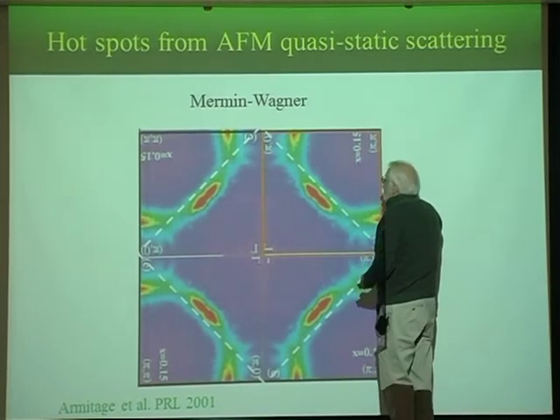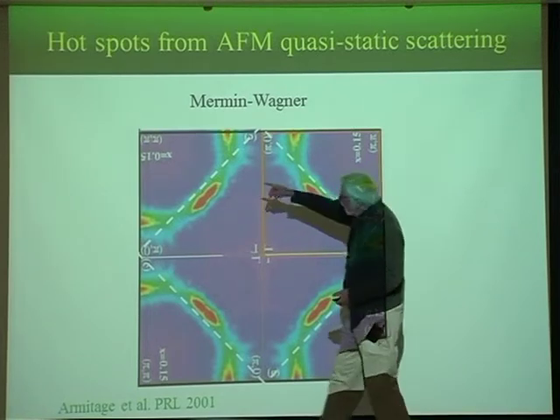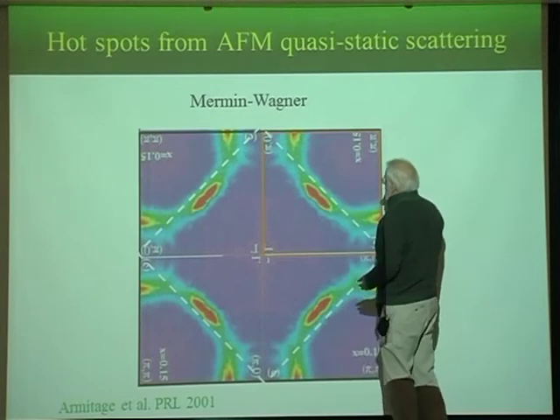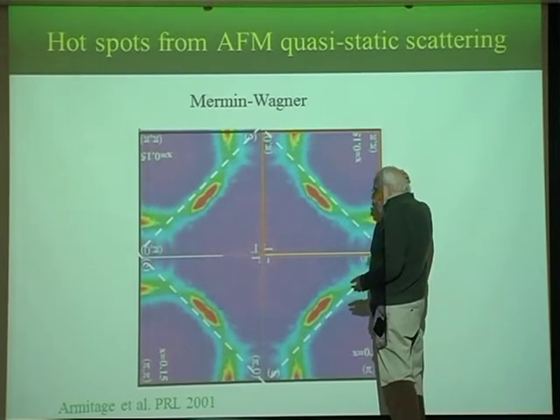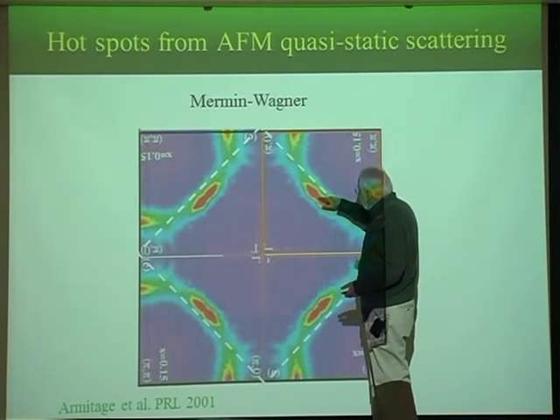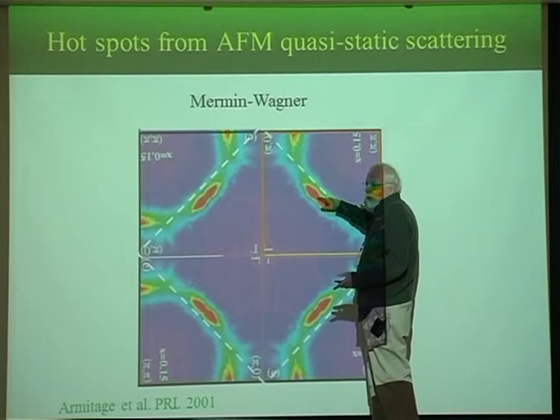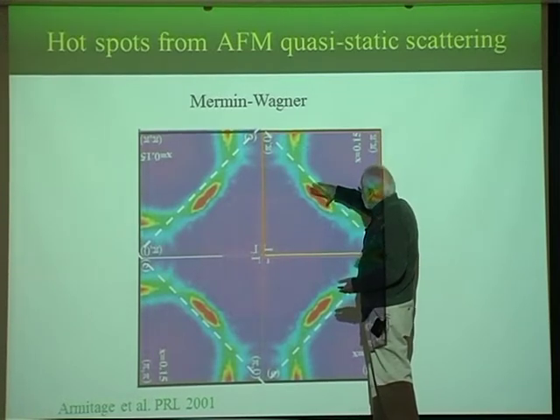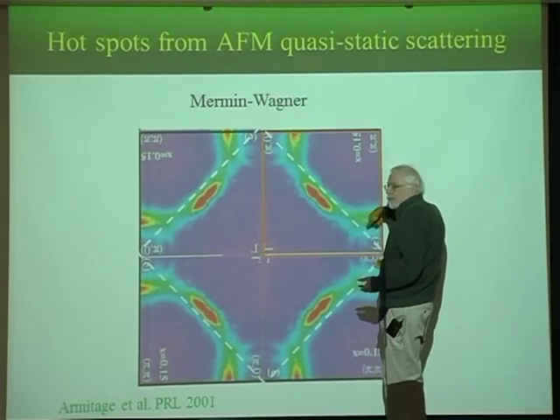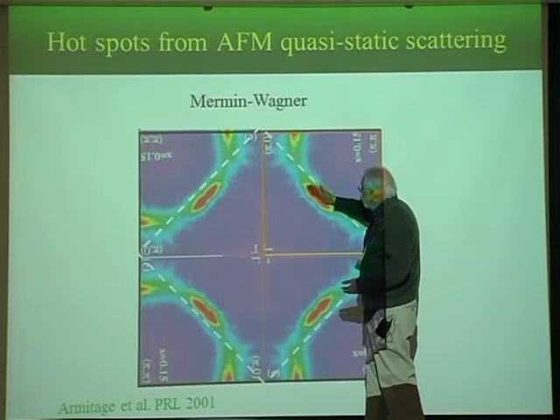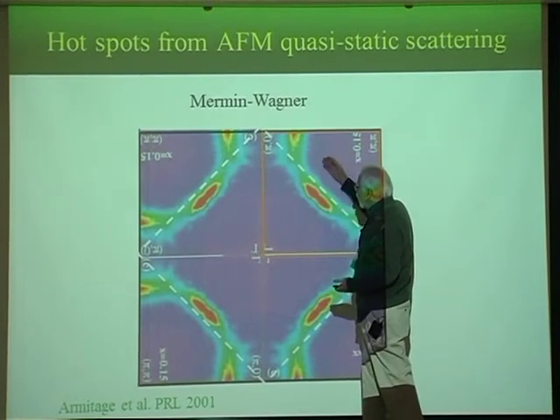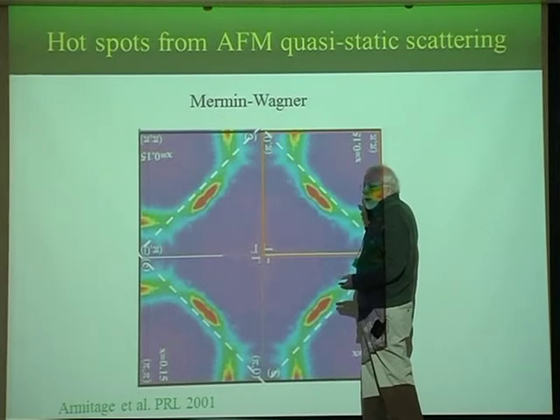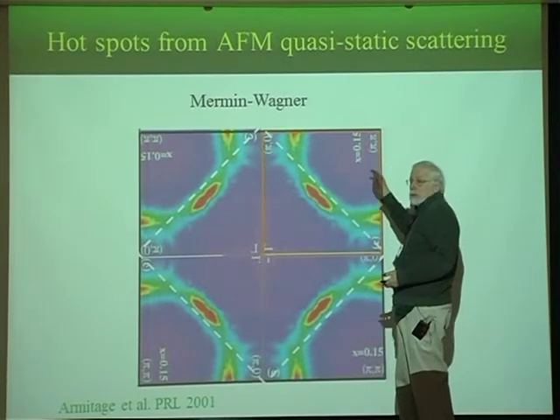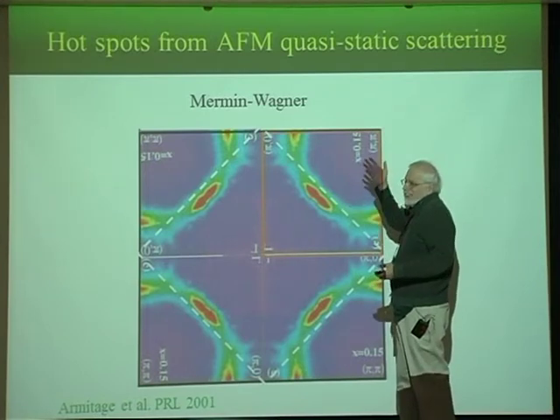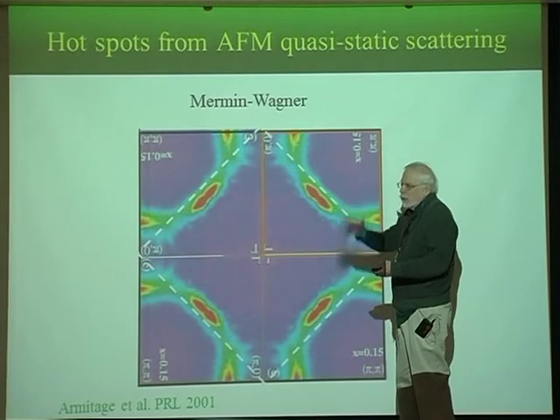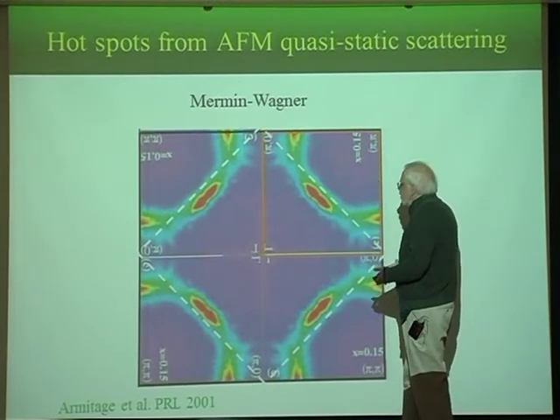Now the color plot is ky and kx. You have guessed, and the color coding is as follows. It's the probability that an electron at this momentum has zero energy. That's it, at the Fermi level. So here, if it was non-interacting, everything would be red. Now it's not the case. This is red, and now this is blue, which means that the probability of having an electron there is very low. The experiment that measures this is angle resolved photoemission spectroscopy. It's called ARPES. It's just Einstein and Hertz photoemission, except it's resolved in angle.